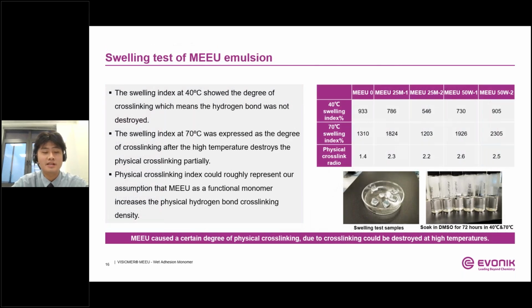So first, in this slide, let me explain what the swelling method is. It is to measure the degree of cross-linking. In the specific swelling experiments, each paint film sample was cut into a regular cube of appropriate size, soaked in DMSO solvent, and placed in an oven at two different temperatures, 40 and 70 degrees. The swelling index at 40 degrees showed the degree of cross-linking when the hydrogen bond was not destroyed, while the swelling index at 70 degrees represented the degree of cross-linking after high temperature destroyed the physical cross-linking partially. The physical cross-linking index is the 70 degrees index divided by the 40 degrees index.